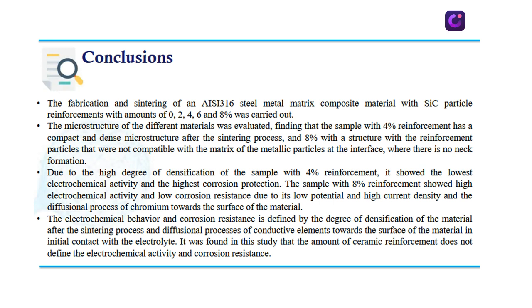Due to the high degree of densification of the sample with 4% reinforcement, it showed the lowest electrochemical activity and the highest corrosion protection. The sample with 8% reinforcement showed a high electrochemical activity and low corrosion resistance due to its low potential and high current density and the diffusional process of chromium towards the surface of the materials.